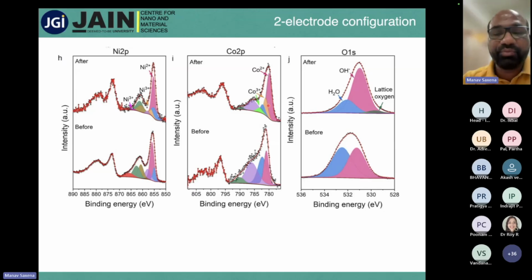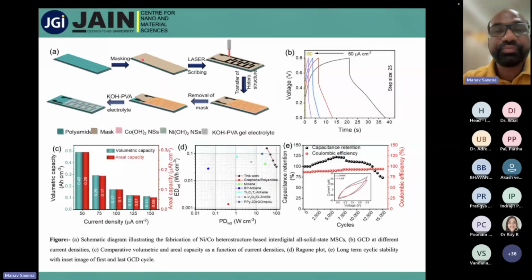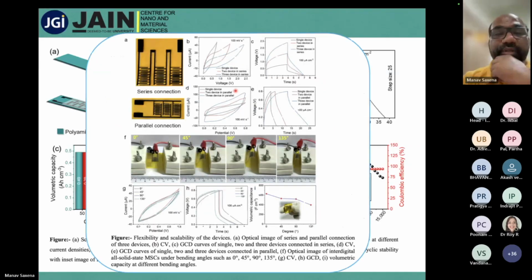For some portion, we have done the quantification based on the XPS analysis, and we have also looked at oxygen, the lattice oxygen, and we can see the hydroxide also. And for the same material, we have fabricated a flexible device where we can see that up to 15,000 cycles, it is showing a good capacitance retention. And this device is quite transparent and flexible.